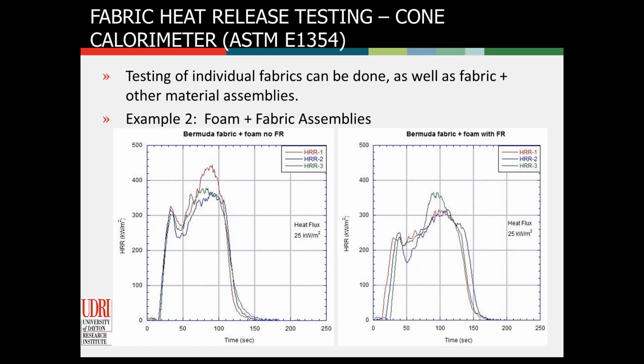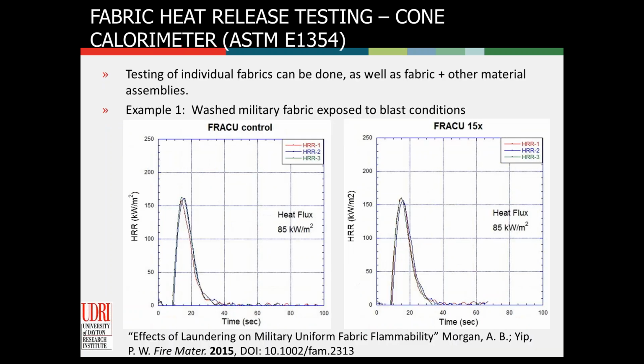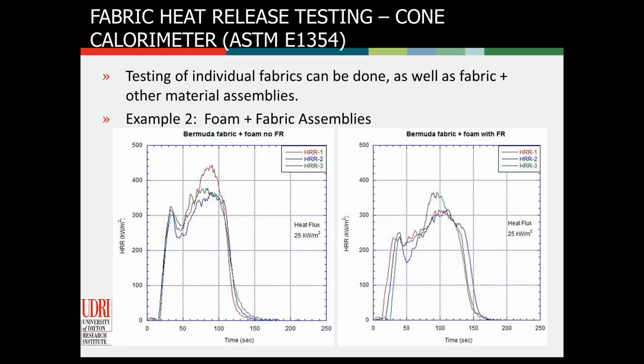But if you test the individual components, you'd see a much different picture. If you just tested the fabric, you'd probably see something more like this slide with a single peak, and then the foam would have its individual peaks. But when you test the two together, you get a little bit better insight. And again, you're going to quantify some of the heat release performance and how flammable it is.